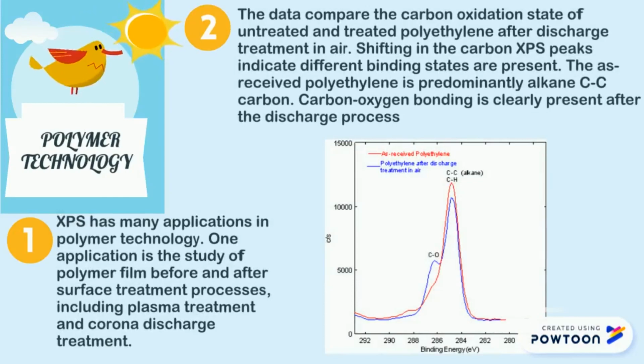One application is the study of polymer film before and after surface treatment processes, including plasma treatment and corona discharge treatment. The data compared the carbon oxidation state of untreated and treated polyethylene after discharge treatment in air. Shifting in the carbon XPS peaks indicates different binding states are present. The untreated polyethylene is predominantly alkane C-C carbon. Carbon-oxygen bonding is clearly present after the discharge process.